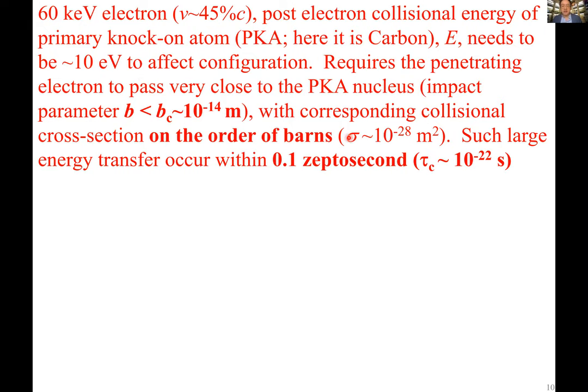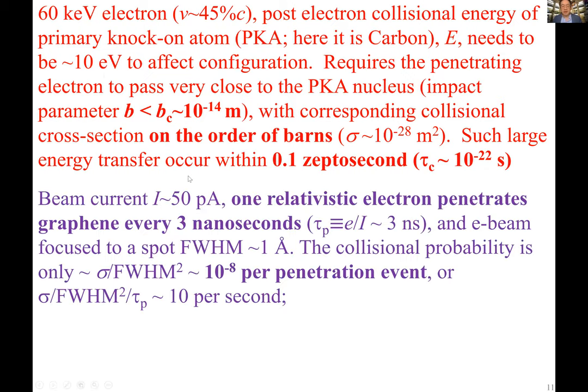So the cross section to give this kind of energy is just on the order of a barn. A barn is a nuclear quantity, so it's basically this squared. And that energy transfer happens on a 10 to the minus 22, so zeptosecond, time scale to give the energy to the nucleus. But that's not what happens in most of the cases.